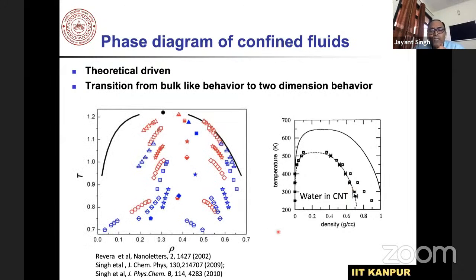So we used an extensive simulation method, and this is just in reduced units of temperature and density. What I'm plotting here is basically a simple system, such as your argon-like system, not even water. Okay, we have done it for water, and we have done it for many systems. This solid line represents a typical temperature-density phase diagram. And what you see here is the different nature of the phase diagram as we squeeze the fluid from bulk-like, 40 nanometer, down to around 2 nanometer. Eventually, we observed a very non-monotonic, very complex behavior for a simple fluid when we bring this fluid between two plates and bring them very close.